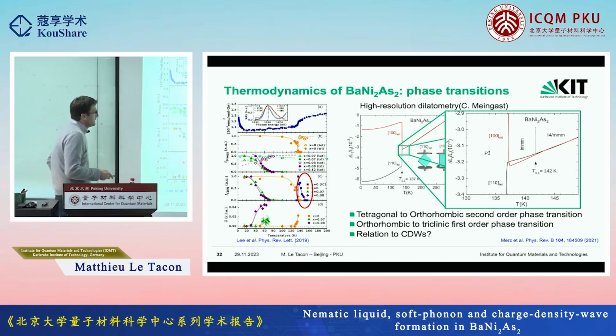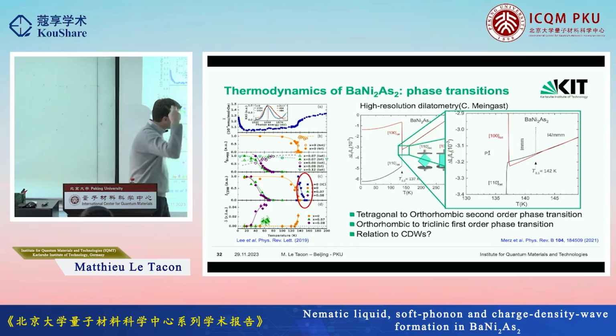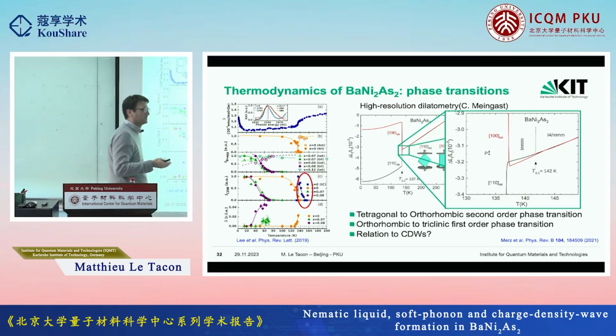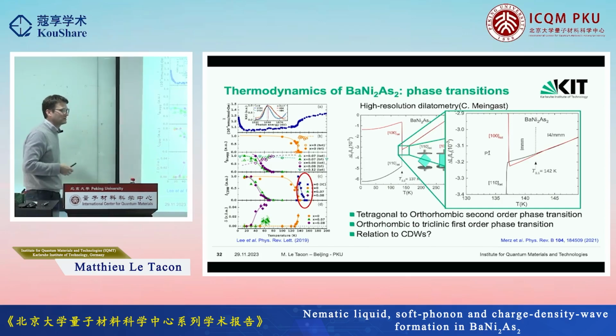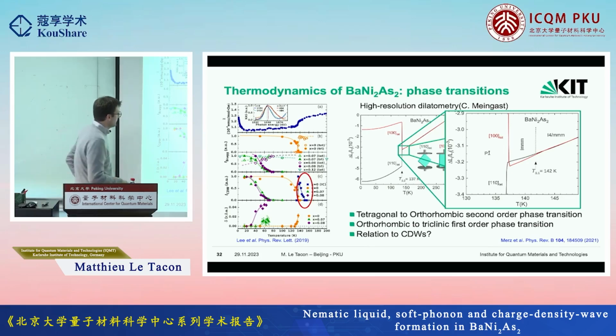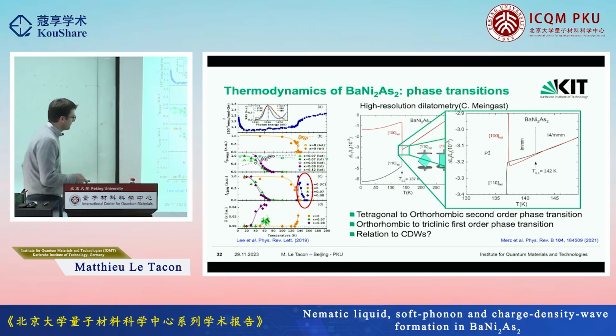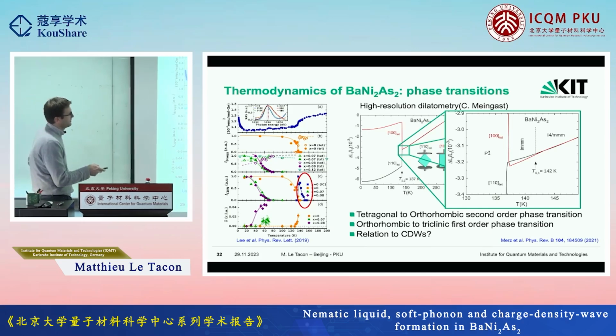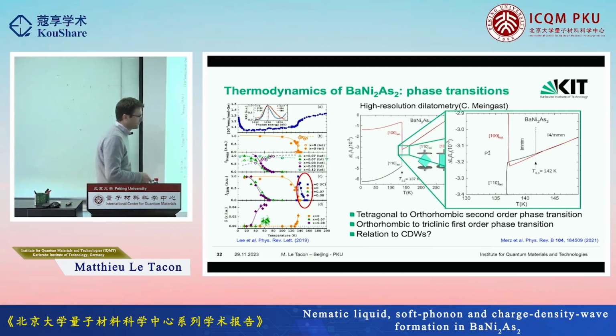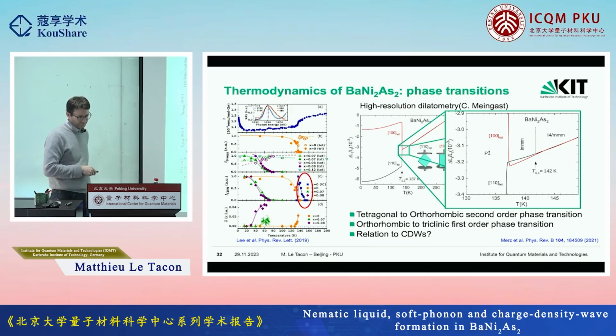I started this talk saying that one thing that was interesting in the system is that we had this incommensurate charge density wave, but so far I have not really said much about it. So this was studied by the group of Peter Abbamonte when they looked at the incommensurate charge density wave. This forms at a temperature which is a bit above the temperature of this tiny orthorhombic distortion. And so we tried to understand how you relate this orthorhombic distortion with the charge density wave.